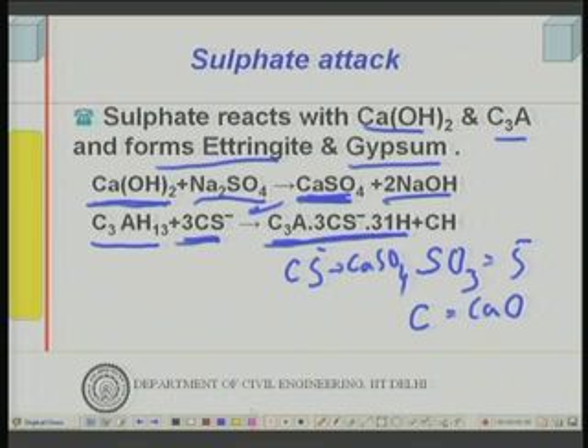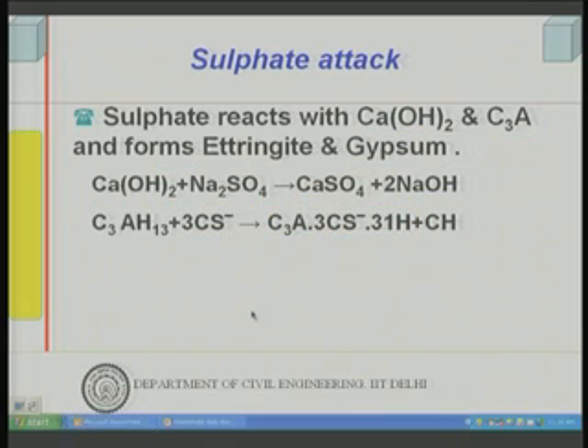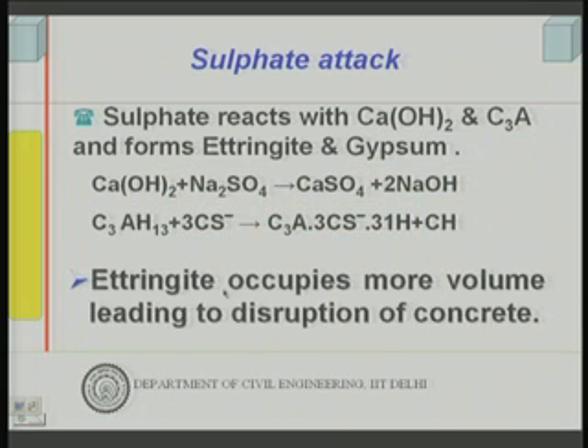This is ettringite, which is volume expanding and occupies more volume. So, the original volumes of the reactants were something like this, now it wants to occupy more volume and you have surrounding material all over the place. So, it will exert pressure onto those surrounding materials and eventually cause cracking of the surrounding cement paste. So, ettringite occupies more volume, leading to disruption of concrete; there will be cracking, and spalling of concrete will come out. So, that is what a sulphate attack is.